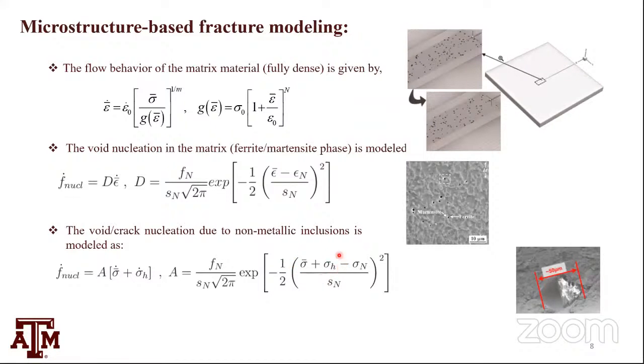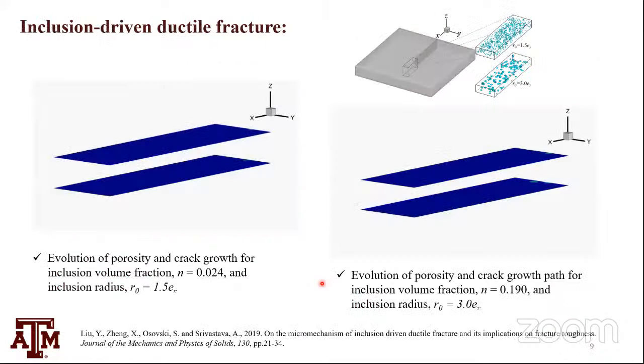In summary, it's a scalar measure of a maximum principal stress, a very approximate zero-order approximation, but gives you a driving force for stress-based nucleation. With that, it's done.